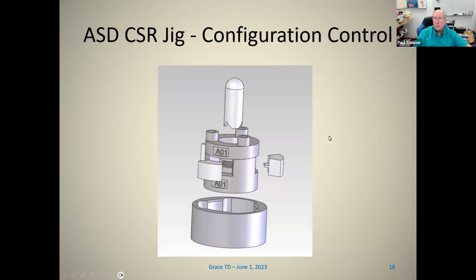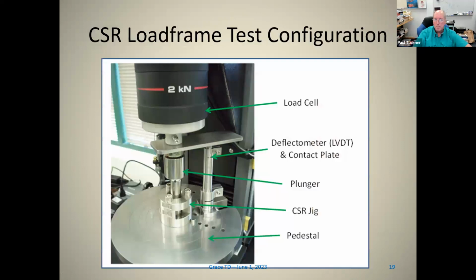One of the unique things about the ASD jig is they use a centering feature which uses wedges and a centering cup, which centers both the shims and the specimen in the jig, which is important. And then I developed an indenter pin, which has a tripod base and a hemispherical head, and it's hardened so that it works really nicely to accommodate off-perpendicular loading in your test configuration. Nobody had really done that, and it really makes a difference in the quality of your load deflection responses.